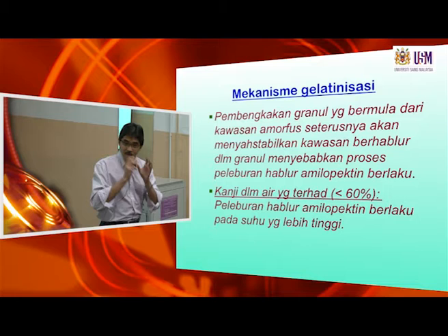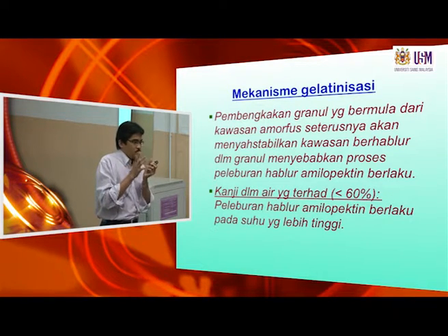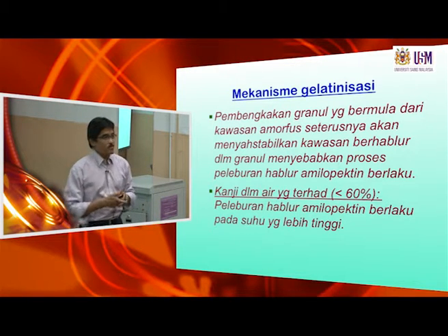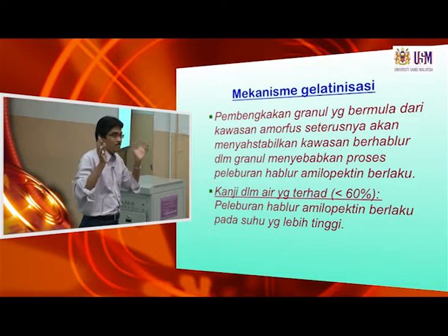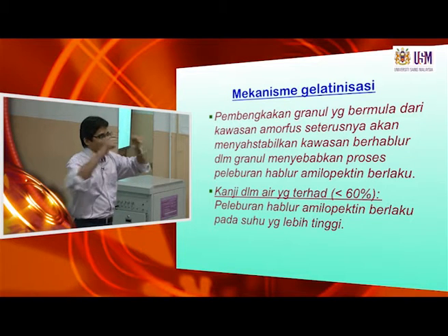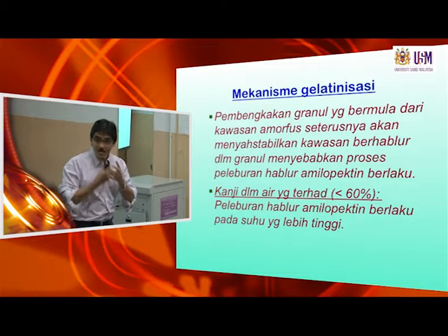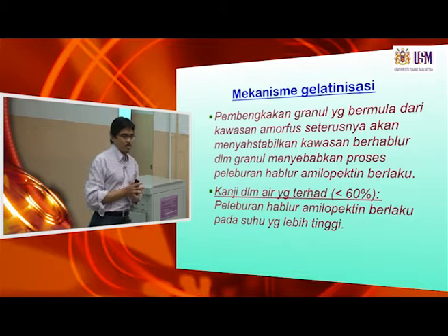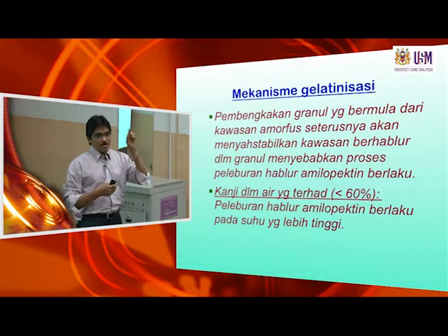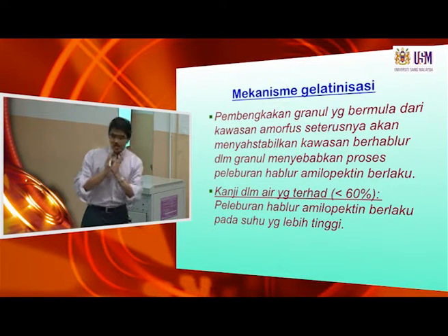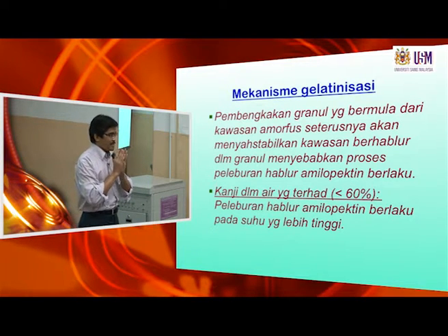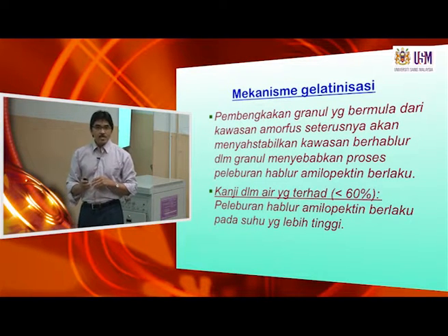Because starch is initially in a granular form, the water will have to penetrate the granule before it can be absorbed by the amorphous region in the granule. But if you have sugar in the solution, the sugar is in a free form, more open compared to the granule structure, so it will bind water easier and faster than the granule. So more water will be bound by the sugar, and less water would be available for the starch granule. So in this situation, when we add more sugar, less water would be available for the starch. So the mechanism of low moisture gelatinization would now predominate.